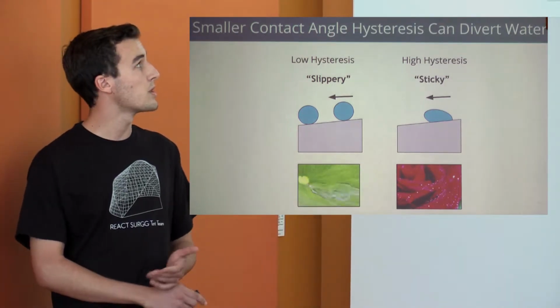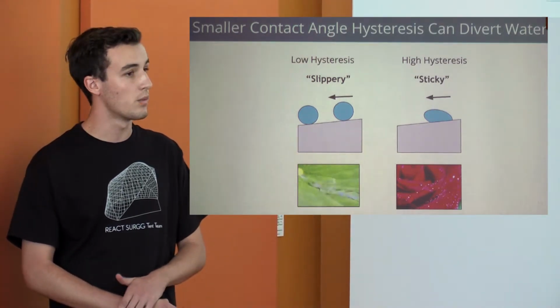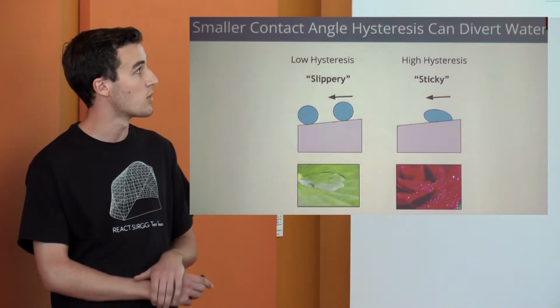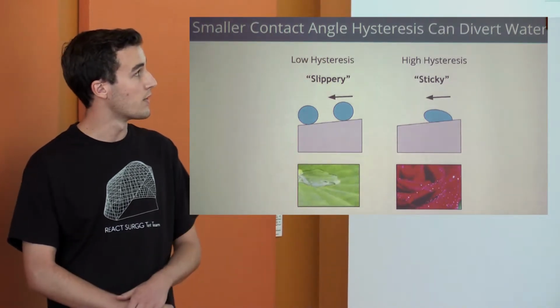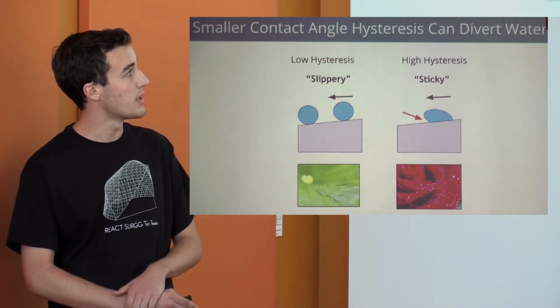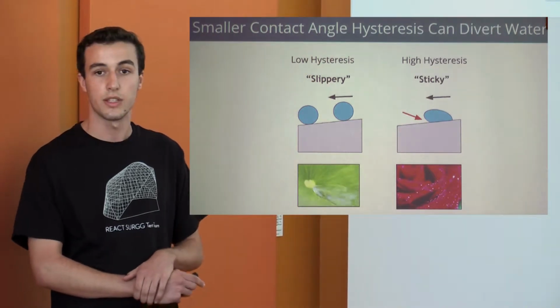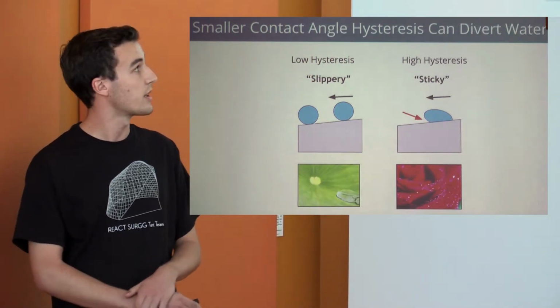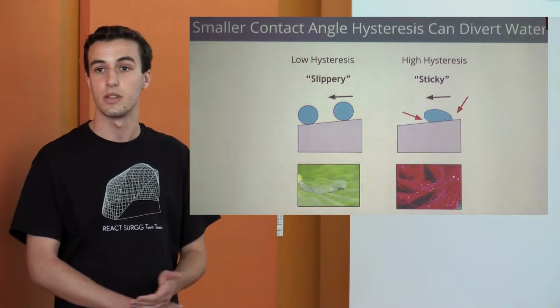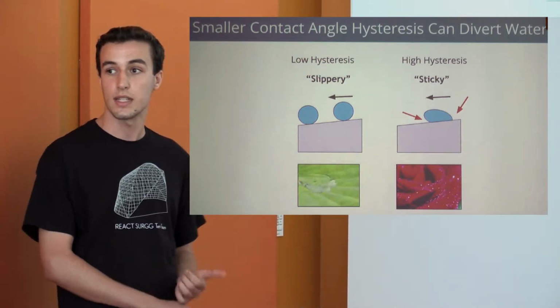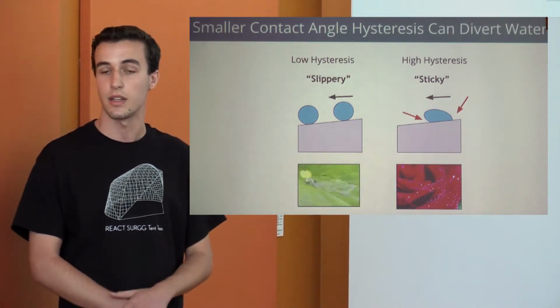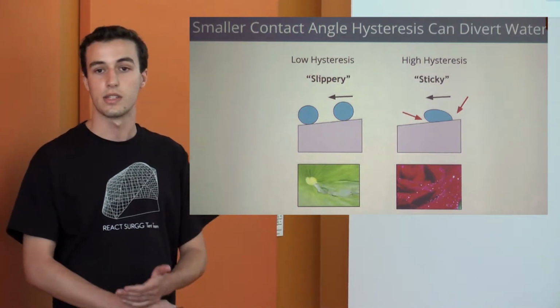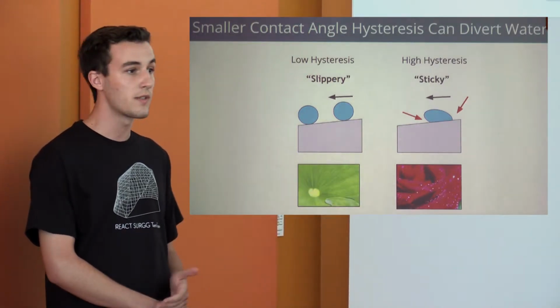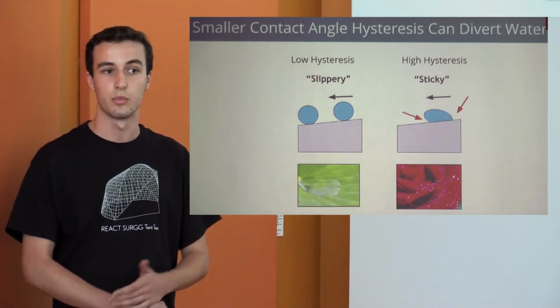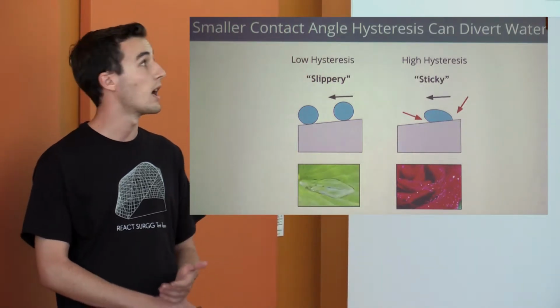To measure hysteresis, one way to look at it is to take a drop of water on an angled surface and measure the contact angle on the advancing side and the contact angle on the receding side, and take the difference between those two numbers. The contact angle hysteresis, this difference that you get, is a very good indicator of how sticky or slippery it will be. So a slippery surface will have a very low hysteresis, and a more sticky surface will have a higher hysteresis.